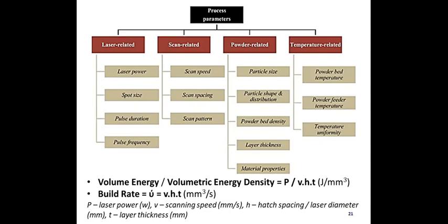The volume energy, or volumetric energy density, is an important factor to be considered for any material to be printed under a laser. A few researchers calculate the volumetric energy density considering two parameters, laser power and scan speed. Another set of researchers calculate it from laser power, scan speed, and hatching space or laser diameter. Most researchers consider laser power, scan speed, hatch spacing, and layer thickness. And build rate will be calculated using scan speed, hatching spacing, and layer thickness.